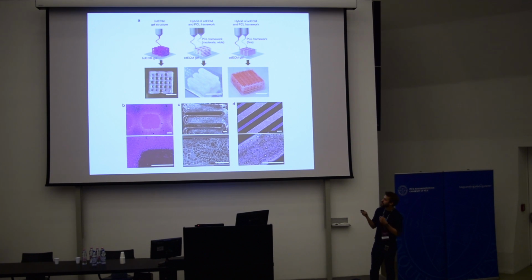And so people have been doing this with bioprinting as well. What they do is they print out a thermoplastic with one of the extruders. And then in between, they put in cells, with the ECM-based structure of either cartilage cells or bone cells. The idea there is that you can then take this, mature it, implant it, the thermoplastic will degrade away, and then you're left with the cells maturing and growing and releasing their own scaffold at the end of the day.